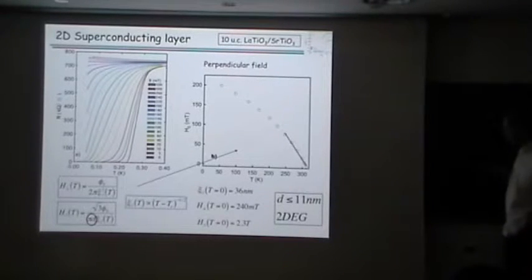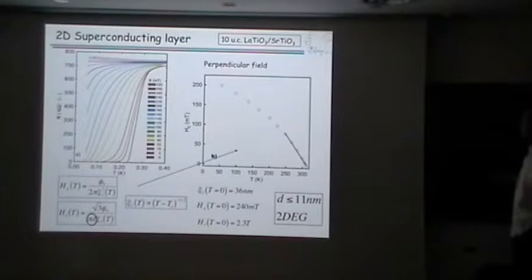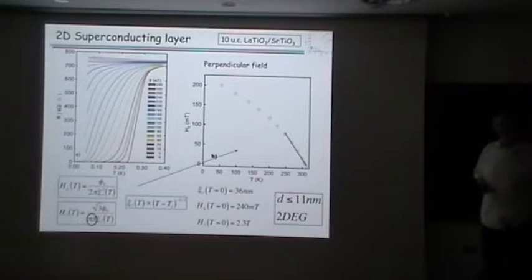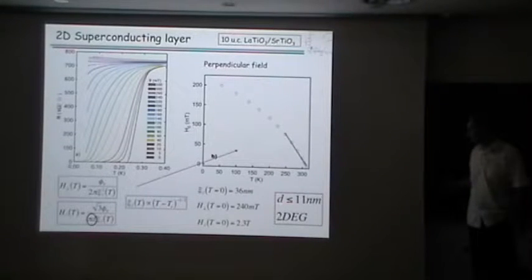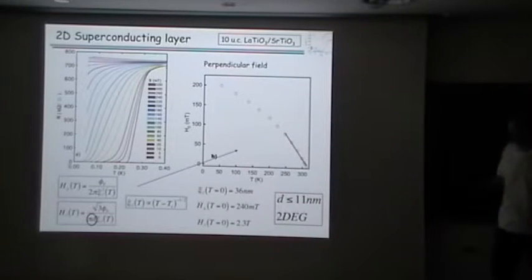Then since it's a superconductor, you can measure the critical field, and it's a very good method to get the thickness of the gas. In our case, we are sure it's below 10 nanometers. Probably, yeah, I mean, this is an upper bound because this is the limit of the precision of orientation of the samples in the dry field. So the coherence length is like 36 nanometers, and that means it's just a regular conductor, a superconductor, nothing special about it.